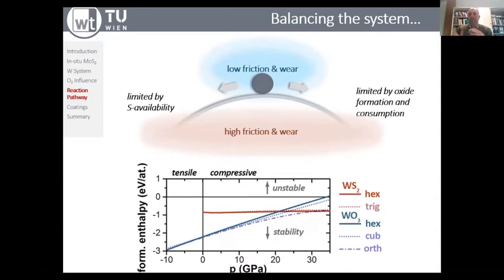So we have a kinetic hindrance in the beginning, but by the interplay of temperature and contact pressure, you might even push the system to a higher stability of the tungsten disulfide in the system, which is not to be expected because usually the metal oxides are rather stable and you can find them predominantly in the contact. But by raising the temperature, by raising also the contact pressure, you can even shift the system. And this is clearly proved by the DFT calculations, where you have a region with a more stable tungsten disulfide that is sketched here in red. You see that this blue line here indicating the tungsten trioxide, there's a crossing point here, or a junction point, where the WS2 actually starts to be more stable.